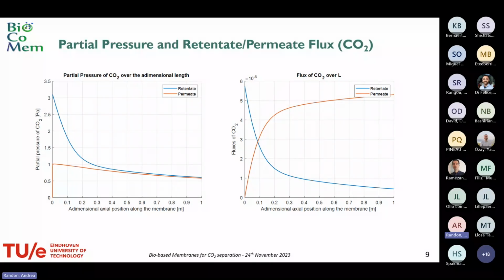As you can see, the CO2 is the most permeable component, and then the partial pressure is diminishing really fast. And on the other side, you can see the flux of the CO2, the intramembrane flux over L, from the retentate and permeate side. You can see the retentate in blue and the permeate in orange. As the driving force is high, the permeate flux is increasing pretty fast, and as it is diminishing, it is basically becoming horizontal. So this is mainly what we expected for the applications, so the removal of the CO2.